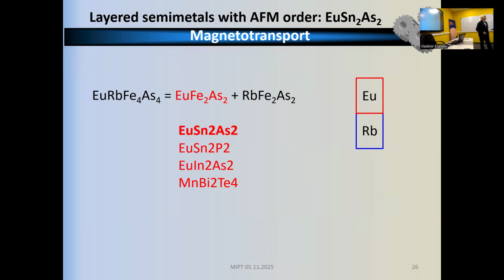It's quite strange that there is some peculiarity in the temperature-dependent current, but still no sign in the gap behavior. It's extremely strange. There was quite a serious theory on this issue by Koshelev and by Pustovit, which predicted indeed that it should affect not the gap, but the superconducting density, the density of pairs. But we understood this much later.